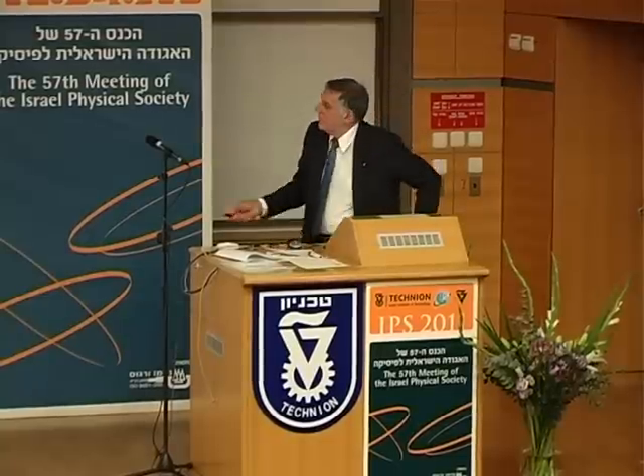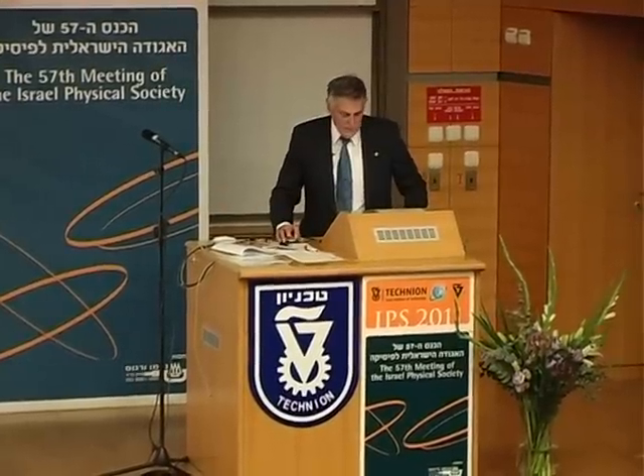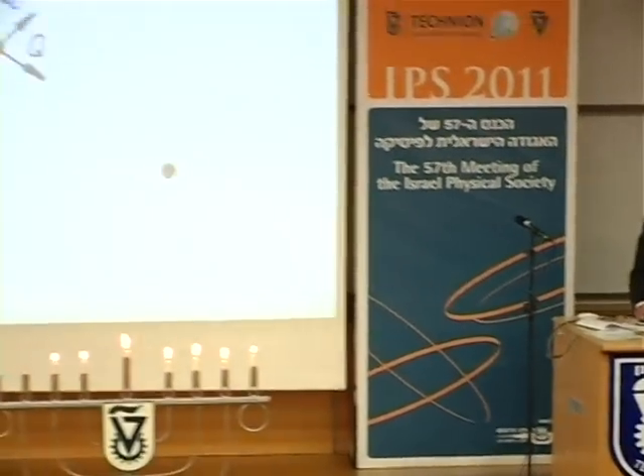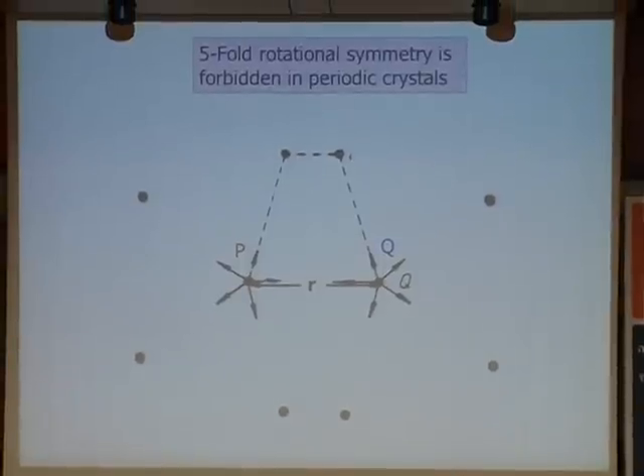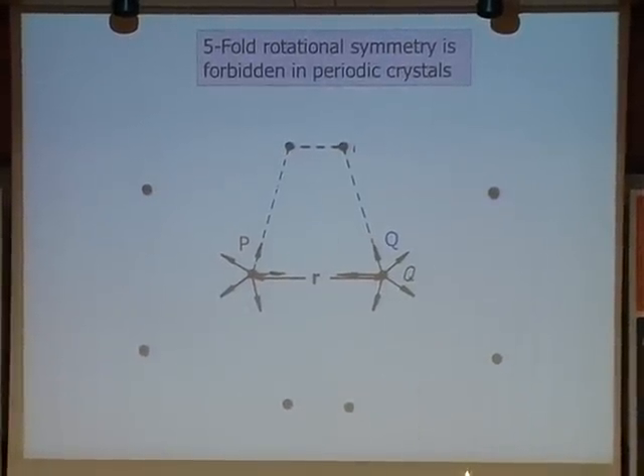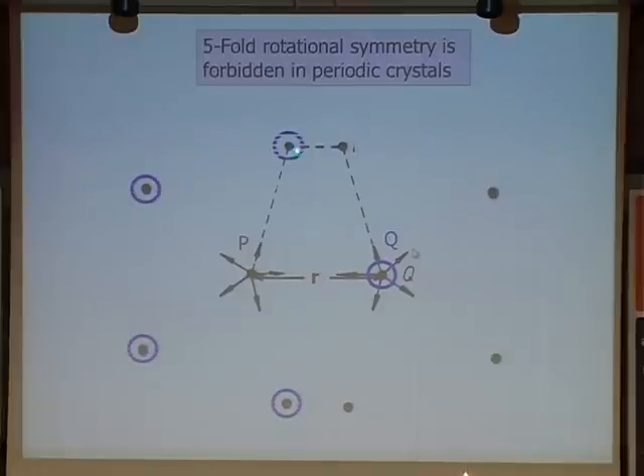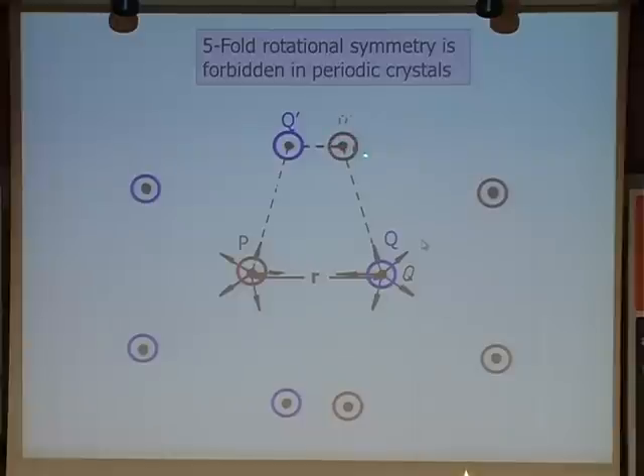Take two atoms, P and Q, such as this and this, and choose the two atoms that are the closest together. So R is the minimum distance in that crystal between two atoms. Okay? And if 5-fold rotational symmetry does exist, then you should be able to rotate Q around P 5 times and P around Q 5 times. And let's see what happens when you do that. So let's rotate Q around P. So we are here, and here, and here, and here, and here, 5 times. And there should be an atom here at Q prime. Then let's do it for P around Q. So here is P, 2, 3, 4, and 5. And there is P prime. And because of geometrical reasons, Q prime, P prime is closer than PQ, and I chose the closest atoms in the structure, so that cannot be, no 5-fold rotational symmetry.